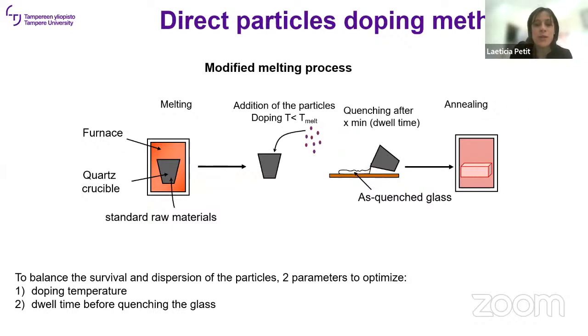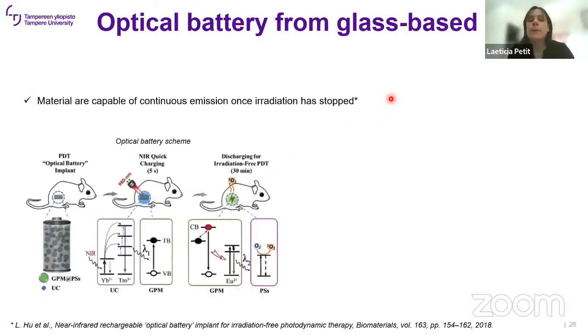So we need to optimize at what temperature we are going to add the crystal, so we don't have corrosion, so they don't remelt. They don't melt in the glass batch, and then the time that we should wait before quenching. So if it's too long, then you have a risk of melting the crystal in the glass, and if it's too short, then you have no dispersion of the particles.